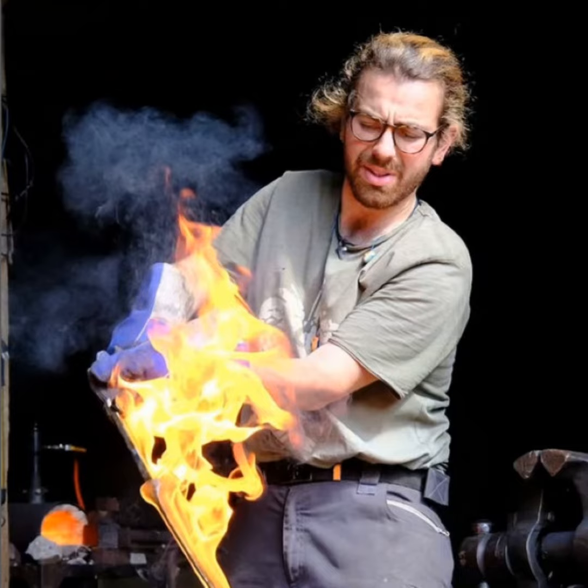What's the grit progression on these stones you're using? Because you said you're starting with 180 or something? Yes, right, it depends. I have a 140 Atoma plate. It's a diamond coated plate, and the diamond plate really leaves very, very deep scratches. So it's really difficult to tell. First of all, I forged the blade. After forging the blade, I forge it really thin. I forge the geometry as far as I can.